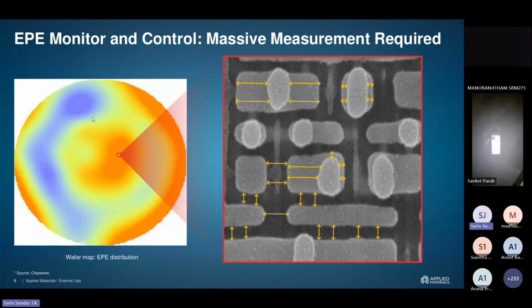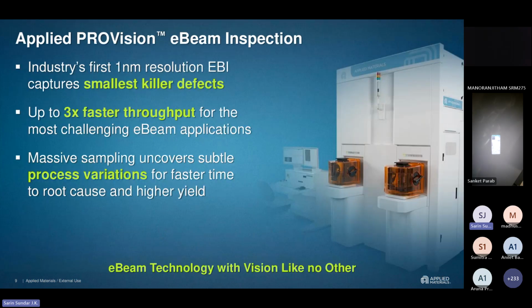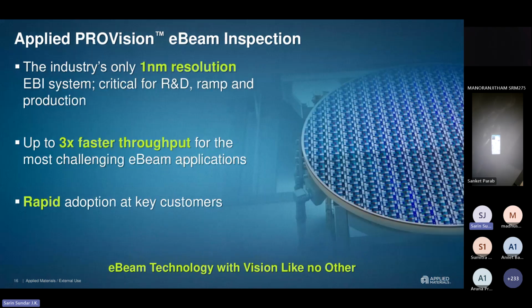For example, on the left-hand side, this is an actual wafer map. If you measure all the defects and make it into a graphical representation, it will look like this, where green is okay and red is a higher level, where the tolerance given is exceeded, a much higher region, right? For example, in your design you may draw a perfect circle or a square, but in the actual manufacturing process, it will look like this, right? So accordingly, the process variation will be there, and as you see, massive measurement is required, even to eliminate the smaller killer defects. And I'll tell you how we actually do this.